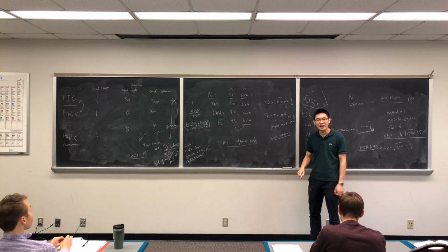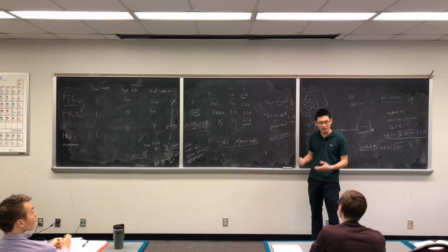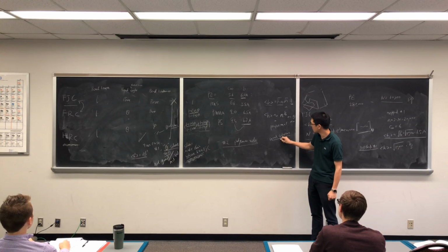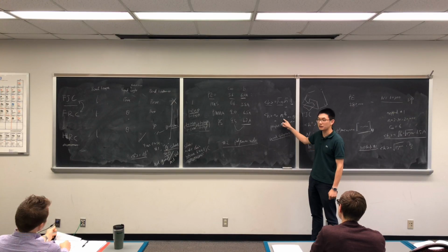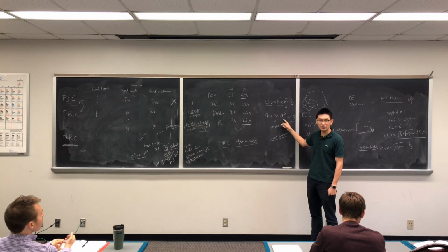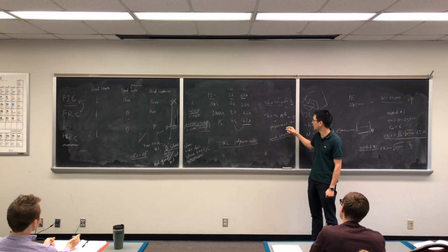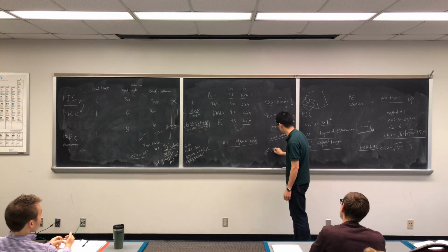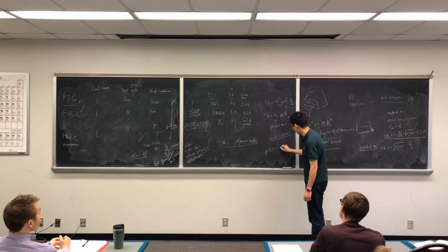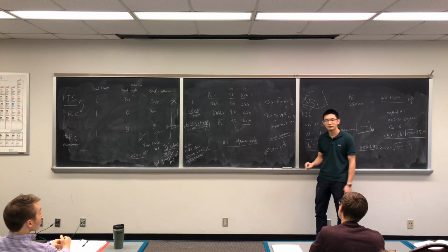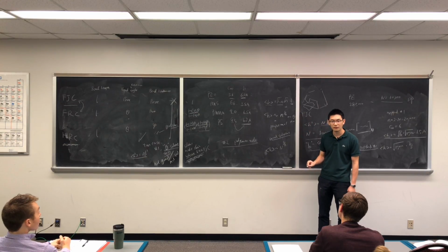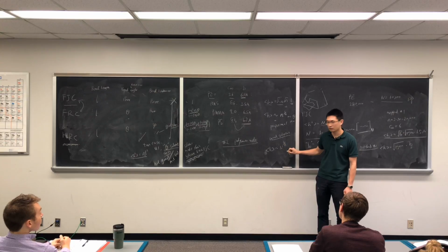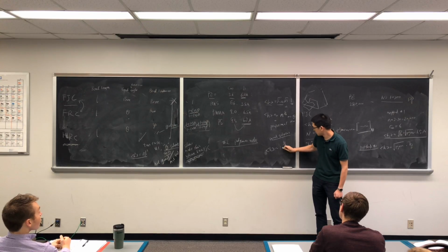So in good solvent, how do these relate to each other? Again, as I mentioned, in this case, good solvent, your chain will be bigger than that. In this particular case, I want to use the proportional term again. So the h will be proportional to n to the 2/3. We will talk a little bit later in this lecture about how we get this. Sorry, this would be small n.